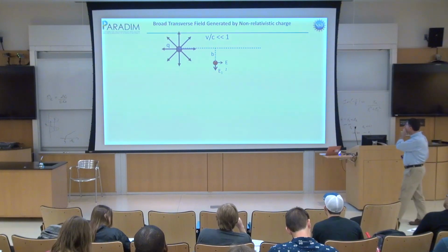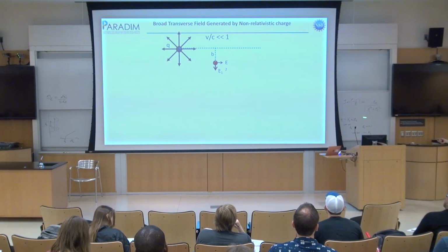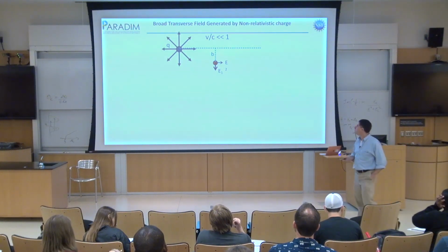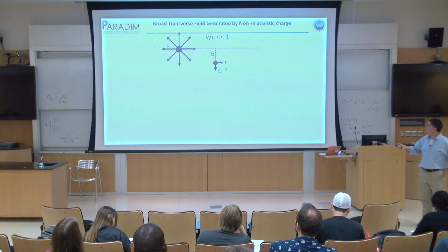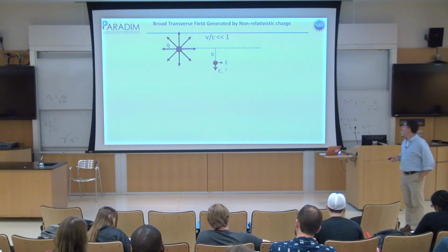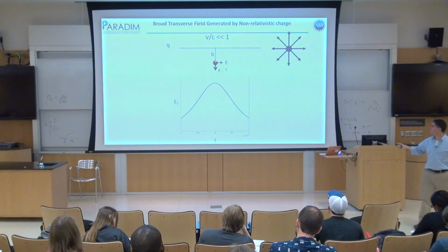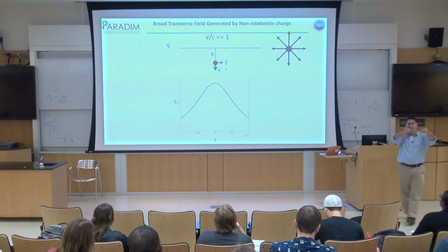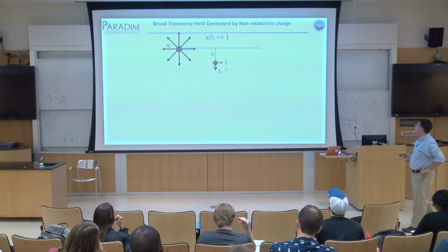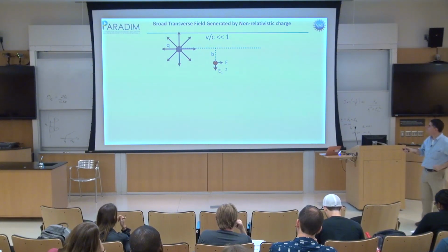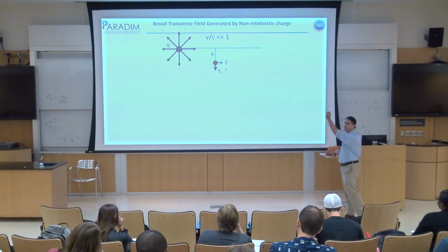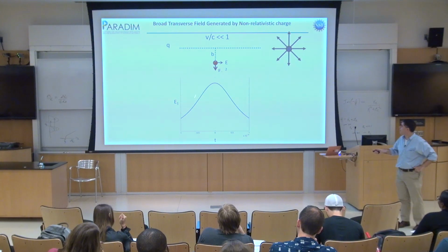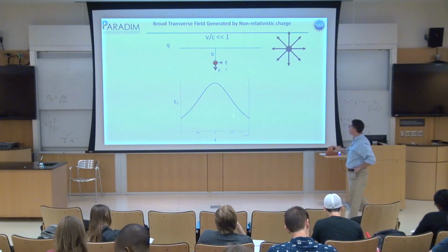Okay, so you're probably wondering, why was I relating my energy loss to dielectric functions? Let me give you a classical picture of EELS. Here is a moving electron, and it has an electric field. So there's my charge, and there's my field lines. And there it is going past a little atom. Imagine my atom is an electron on a spring, a positive nucleus holding an electron in with a Coulomb potential. The moving electron goes past, and it's going to push the electron in the atom away, and then that electron is going to spring back based on its restoring force. So here is the electric field that this atom feels as my electron goes past it. This is a time-varying electric field.